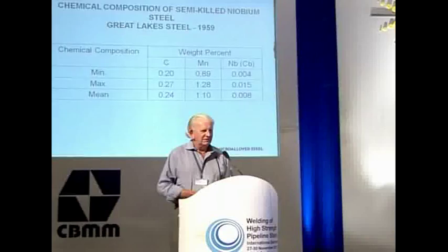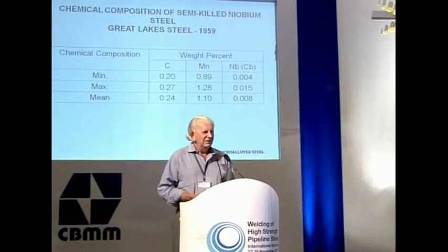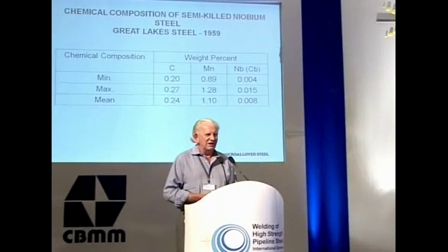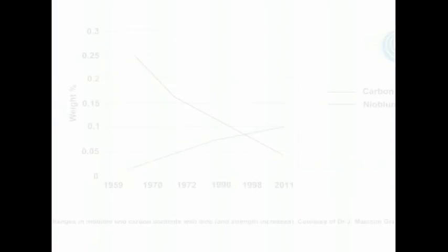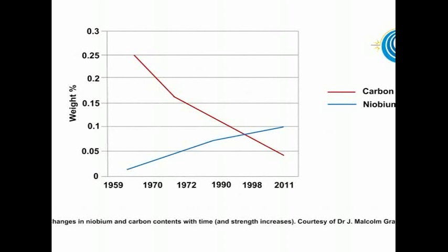Dr. Gray then set the scene for the seminar by presenting a paper detailing the history of the use of niobium in line pipe steels. The story begins back in 1959, when a small addition of niobium, less than 0.01%, was first added to a carbon manganese steel to allow the production of the X52 grade. At that time, a carbon level of 0.25% was fairly typical.